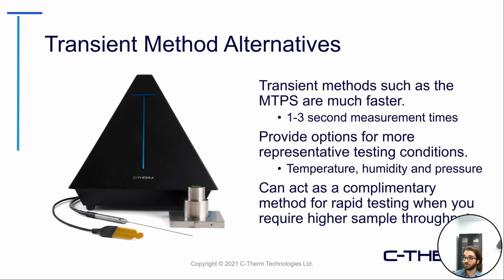So obviously we're really focusing in on different transient methods. Adam went over these a little bit earlier, but on Trident there are 3 different options, all of which provide much faster test times. As an example, with the MTPS you get your measurement times in about 1 to 3 seconds, depending on the samples you're working with. They provide options for more representative testing conditions. These sensors can be placed in varying temperature, humidity, and pressurized environments for this type of test.